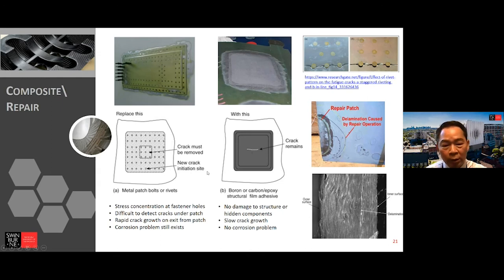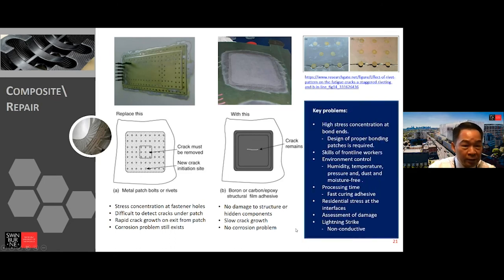So according to the results from different researchers, basically the crack propagation rate for the composite repair is much lower than the metal repair scheme, the traditional scheme, if there's a crack inside. And also, when you look at the problem, for composite repair there is high stress concentration at the bond end. I will talk about it in the next slide, and this is one of the very critical issues.